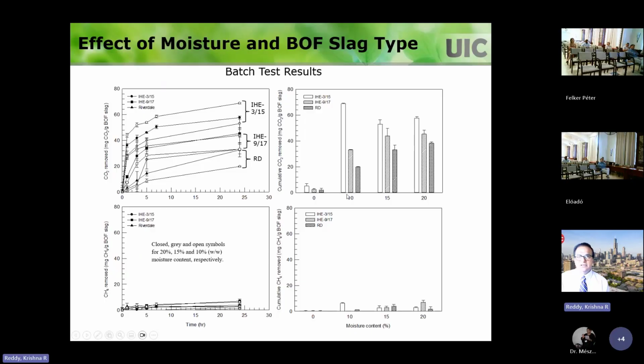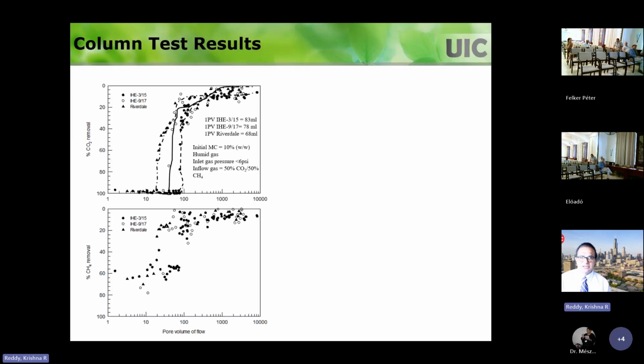One important thing about the efficacy of this material is you need to have some moisture. If you don't have any moisture, for carbonation reactions, they happen in the solution form. So we looked at 10%, 15%, 20%. So at least 10% is good enough for the carbonation to take place. So again, since these cover systems are on the top, when it rains, the water gets into it and the moisture is retained. So you have to check if that moisture retained is enough for these carbonation reactions or not. So the point is, you cannot expect a dry material and have these reactions take place.